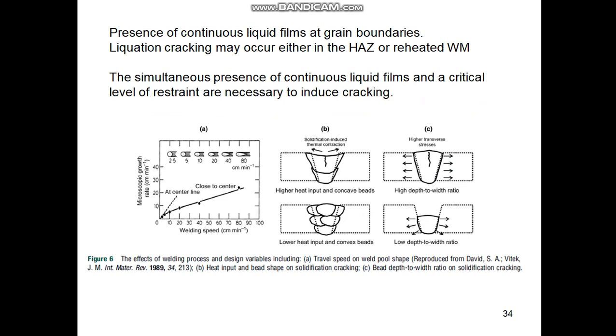It is showing the effect of welding process and design variables, the effect of travel speed on weld pool shape, and the heat input and bead shape on solidification cracking. Just look at this microstructure growth rate in centimeter per minute versus the welding speed in centimeter per minute. You would see that increasing the speed from 2.5 to 5 up to 80 centimeter per minute decreases the heat input, right? So you have to optimize your welding speed so that the weld pool becomes more of an elliptical shape, not the teardrop shape. Had it become teardrop shape, then most of the time the segregation of the alloy elements will be along